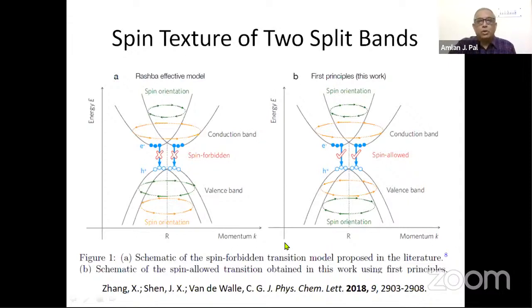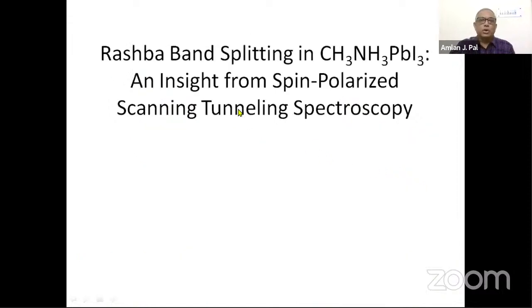So we decided to work experimentally to know the spin states of the Rashba band split bands, because there should be Rashba band splitting in this material, that is well known. The only thing that was not known was the spin texture of the lower of the two conduction bands and the lower of the two valence bands, whether the spin forbidden transition model is valid, or whether the spin allowed transition model is valid. So we did this work with spin polarized scanning tunneling spectroscopy.